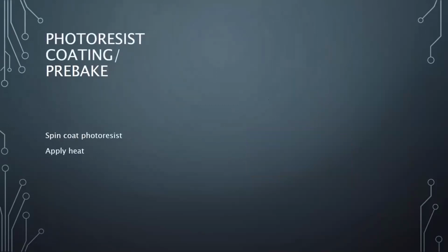The wafer is covered with photoresist by spin coating. Photoresist is dispensed onto the wafer, and the wafer is spun rapidly to produce a uniformly thick layer. The spin coating typically runs at 1200 to 4800 RPM for 30 to 60 seconds, and produces a layer between 0.5 and 2.5 micrometers thick. Runoff from the extra photoresist is removed through a process called edge bead removal to produce a flat layer of resist.